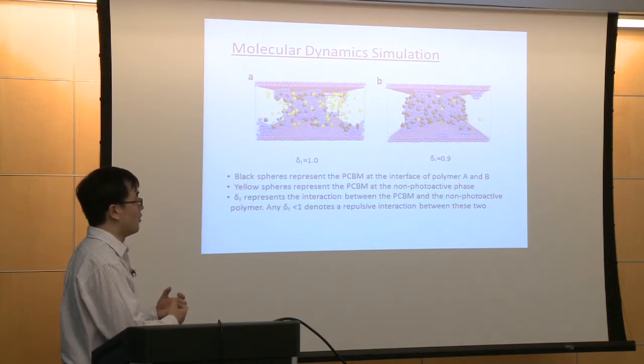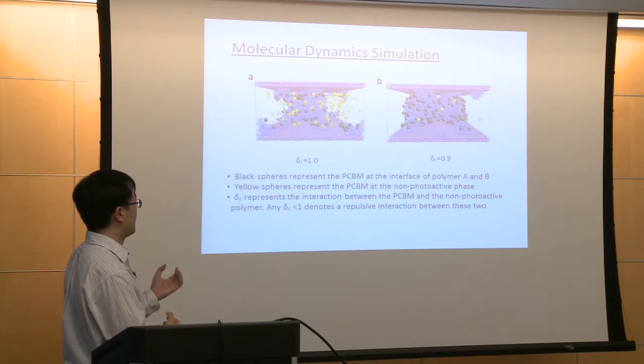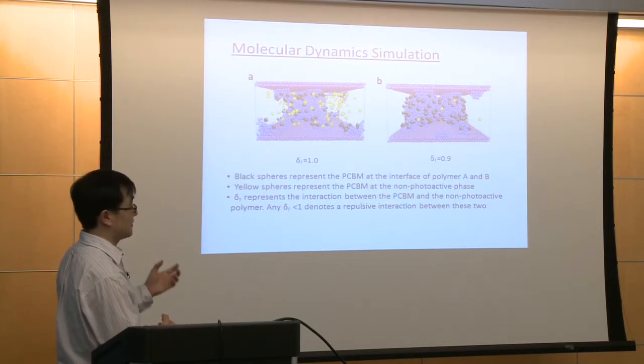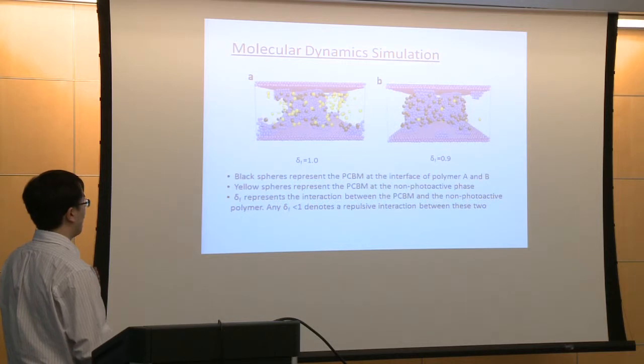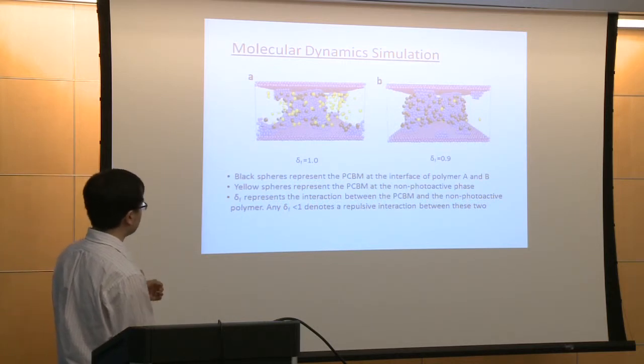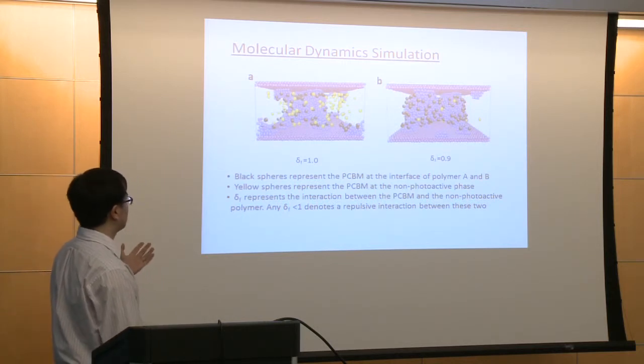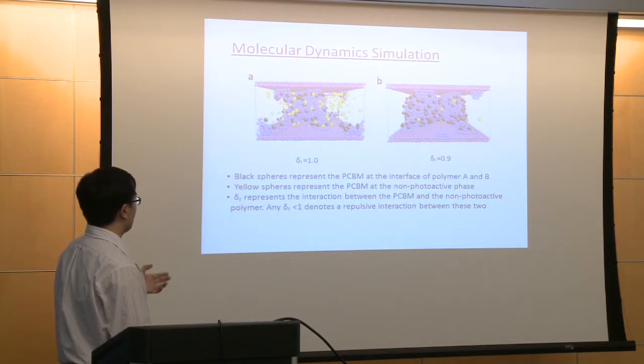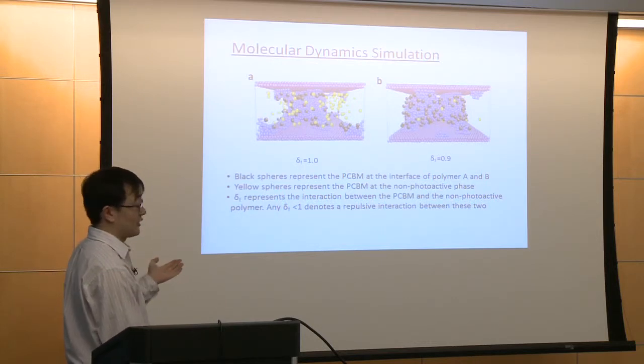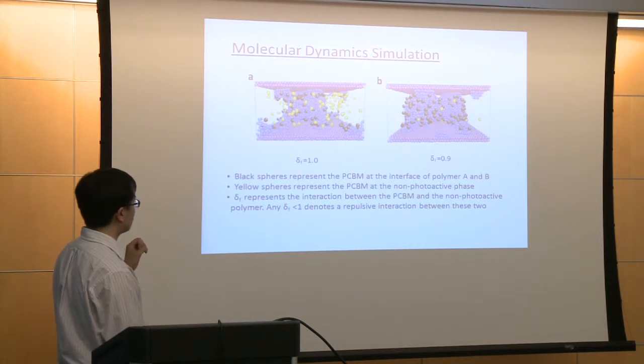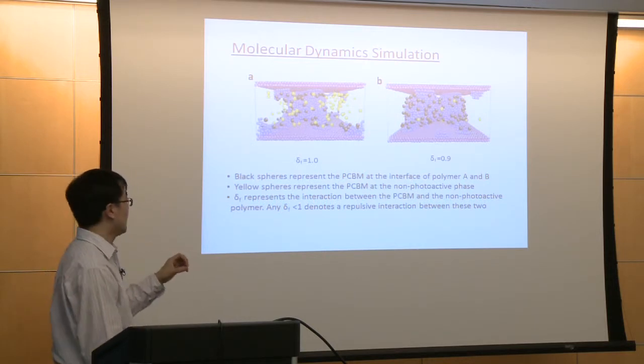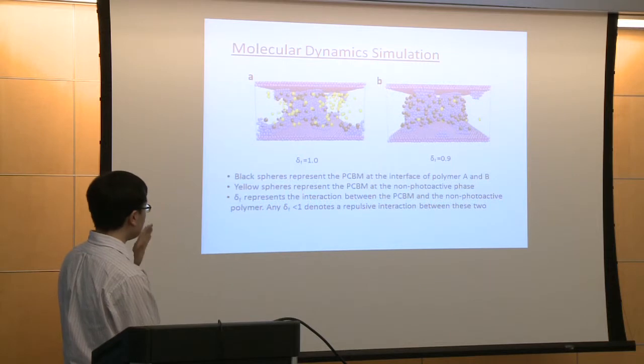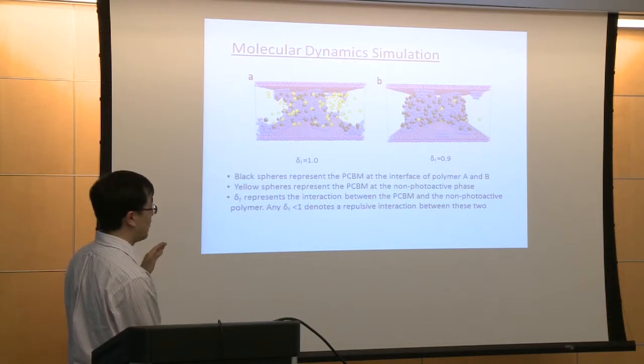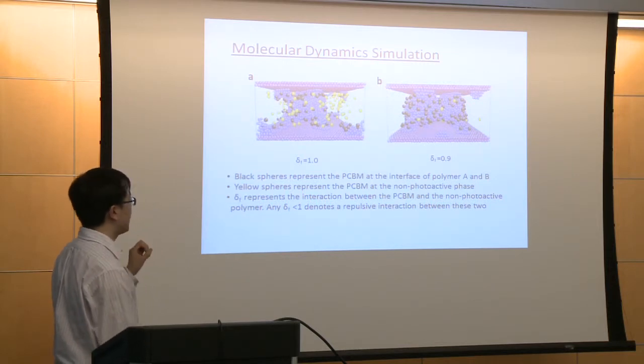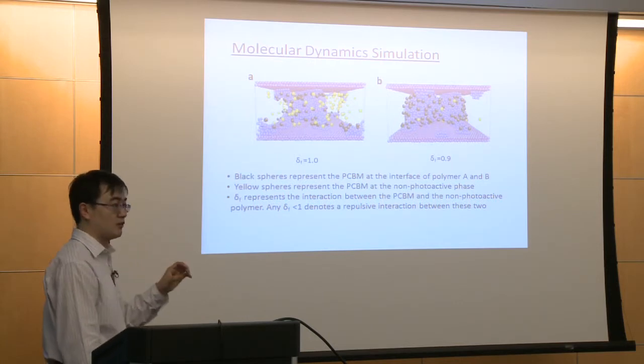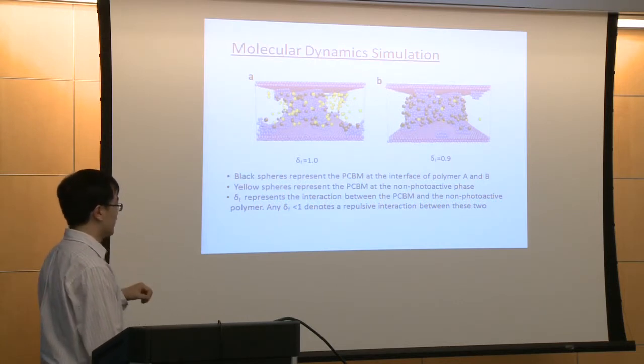And then we need to know whether the PCBM will prefer to segregate at the interface between the P3HT and the other polymer. So here we have 2 situations. We introduce another parameter, which is delta F. Delta F represents the interaction between the PCBM and the second polymer. So whenever the delta F is less than 1, it means there's a repulsive interaction between the PCBM and the other polymer. It's very similar to the previous one.